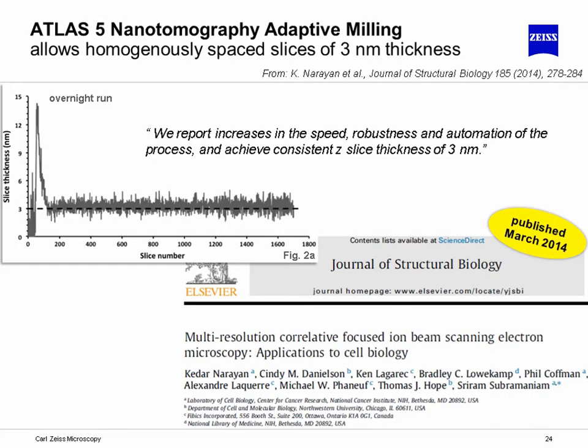The same group at NIH has pushed Atlas 5 even further and reported in a recent publication a consistent slice thickness of 3 nanometers. On the left, you can see a plot out of this publication where you can see how the slice thicknesses are measured as a function of slice number. At the very beginning, the process needs some time to stabilize. It quickly stabilizes, and then it maintains a constant slice thickness of 3 nanometers through the rest of the experiment.